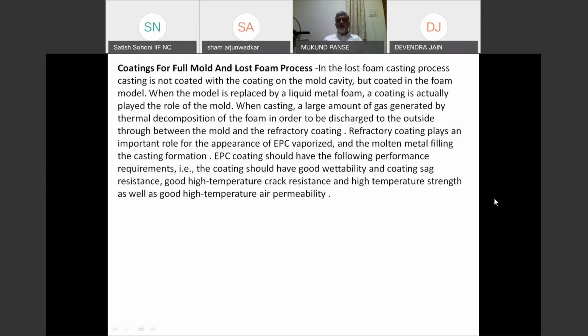Full mold casting: quite a few castings, large castings especially, one-time requirements, are nowadays made with the full mold process. The coating requirements are somewhat different, but much more important in this case. When you are pouring in the lost foam process, the foam pattern is coated first. The mold is not coated. It is coated by one or two coats, dried completely outside or in sun rays or using infrared rays. It is molded, and when you are pouring, a substantial amount of gas is formed when the foam burns.